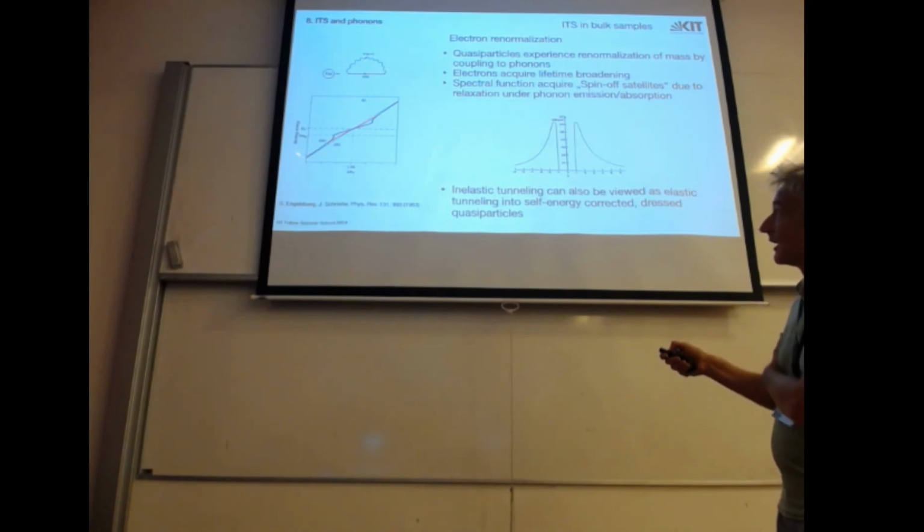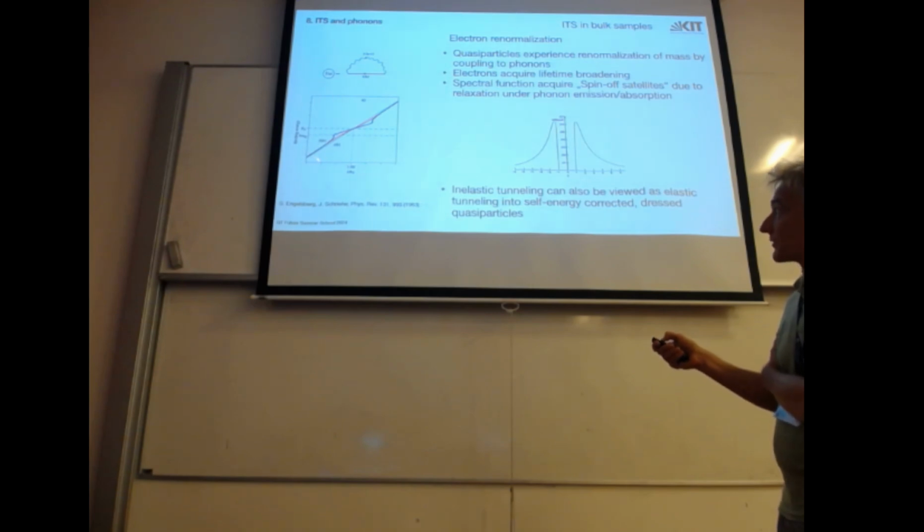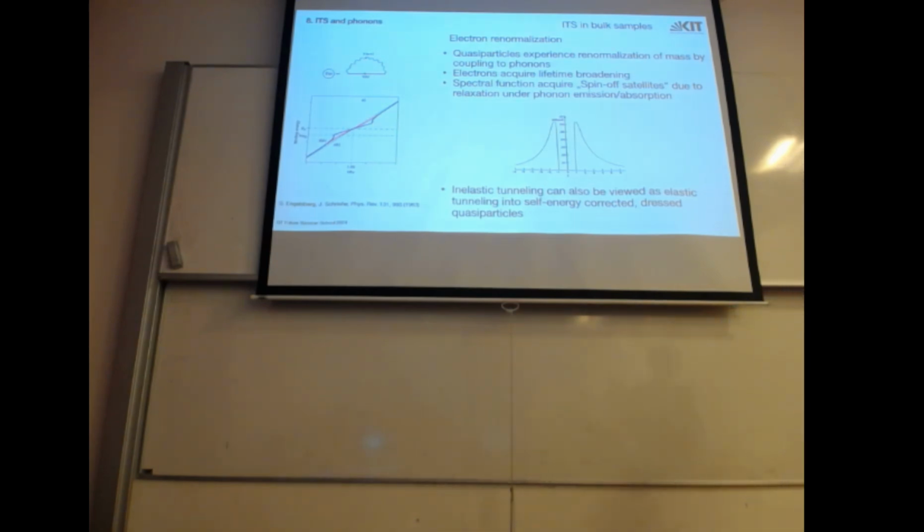This you can see in normal band structure. So we take photoemission data of some material with high resolution, it goes into the Fermi energy, this is linear expansion, A(k,ω), and in the presence of phonons, you get a renormalization of the electron mass in the window of phonon energies. So the effect is that the mass changes.